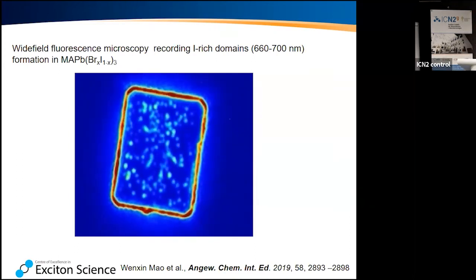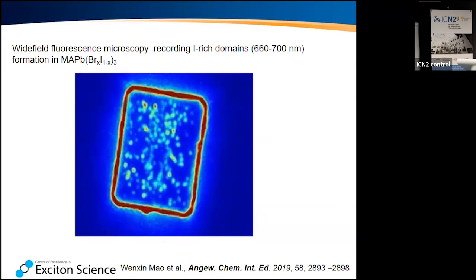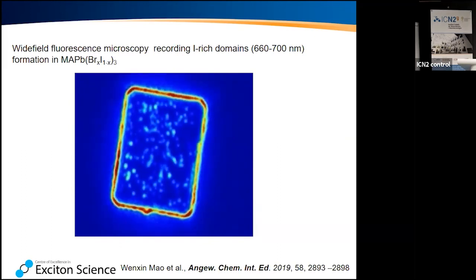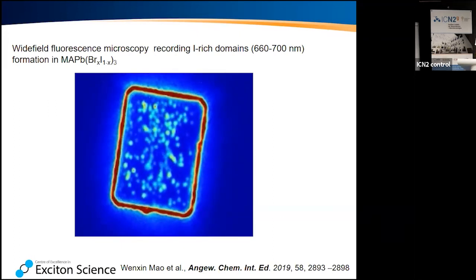And I think a lot of what we see at the boundaries here is waveguiding. So don't look too much at the boundaries, look at the center. And here you can see how these domains are shining up, which are rich in iodide. So here we could show that, unfortunately, that halide demixing that everybody always thought is somehow linked to grain boundaries actually also just as well happens in a single crystal of perovskite.